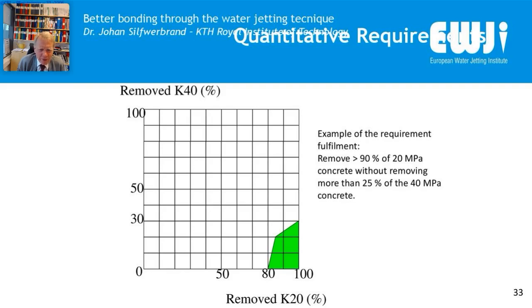And you can see here that in order to use the equipment selectively, the result must be inside the green area in the bottom right of this diagram. And you can see one example of fulfilling the requirements, that is to remove more than 90% of 20 megapascal concrete without removing more than 25% of the 40 megapascal concrete. So it was quite difficult, I think quite strict requirements.